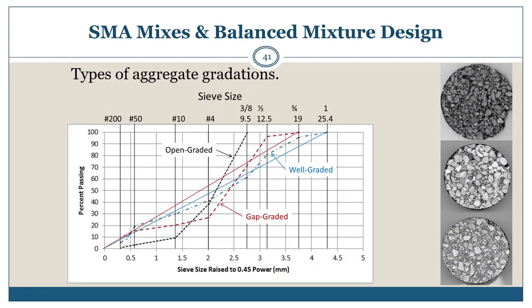Aggregate gradation is one of the more important factors in the balanced mixture design process to establish the job mix formula. This slide simply shows the types of different aggregate gradations. SMA is typically considered gap-graded and only has a small percentage of particles in the mid-range particle size. As shown in the figure, the curve is flat in the mid-size range of the aggregate particles. Gap-graded aggregates are used to obtain uniform textures in exposed aggregate concrete, and close control of mixed proportions is necessary to avoid segregation. Because the aggregates are all in contact, rut resistance relies on aggregate properties rather than the asphalt binder properties to a large degree.